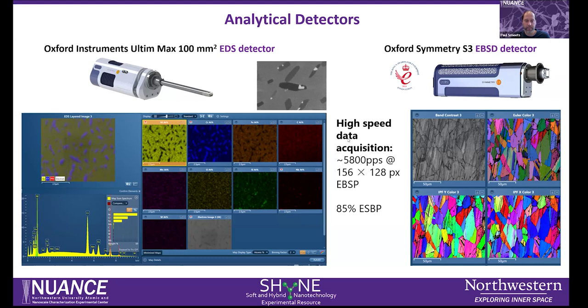So we can acquire high-speed data acquisition of the Kikuchi patterns, now at about 5,800 patterns per second with this pixel resolution. This is an example of that acquisition for a stainless steel sample, where you can see different orientation grains highlighted, and about 85% at this high speed acquisition was correctly indexed.